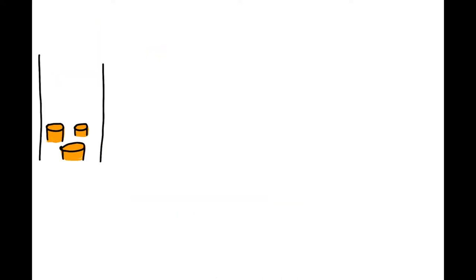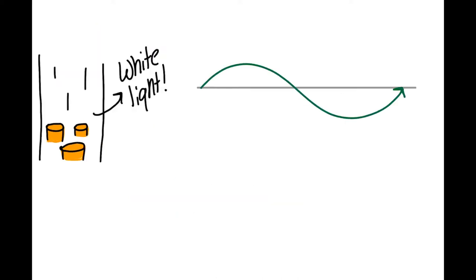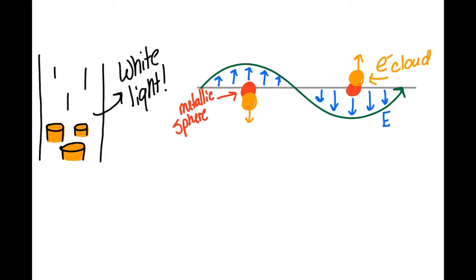When a light beam illuminates the metallic nanoparticles, the nanoparticles display plasmonic effect. This means that the light interacts with free electrons of the nanoparticles to create induced resonant dipoles. These induced resonant dipoles cause the absorption of light at a specific wavelength called the plasmonic resonance which causes the nanoparticles to appear with a specific color.